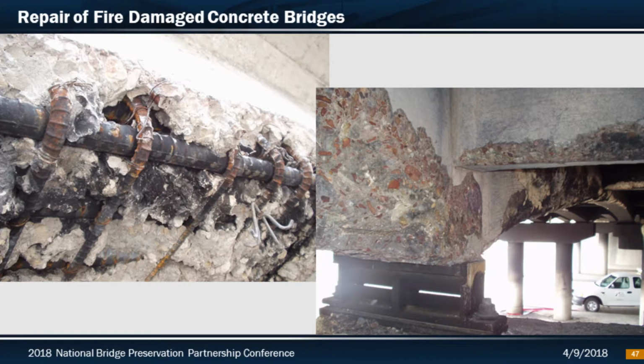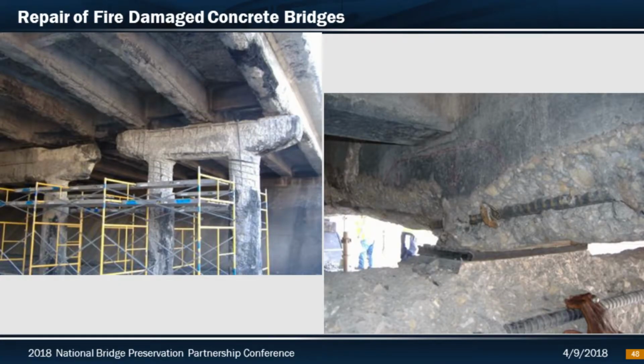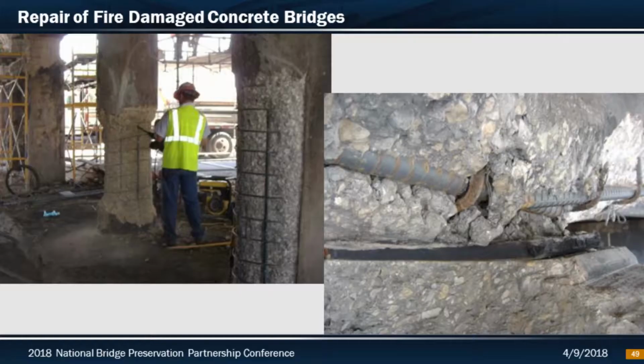It was noted that the concrete cover effectively minimized the thermal effects. It added thermal protection from the fire, so we were losing a couple inches of concrete. Everything below that was in fairly decent condition. It discolored the concrete aggregate. You can see there it's a little pink, and obviously discolored the bearings and the reinforcing steel. That 2 inches of cover concrete is fairly critical in the compression zone in your bent caps and beams, and the tension zones. So we ended up wanting to go back with a full encapsulation of that cap, and again do the beam repairs with concrete repair and CFRP wrapping. That will give us a little bit of additional structural capacity.